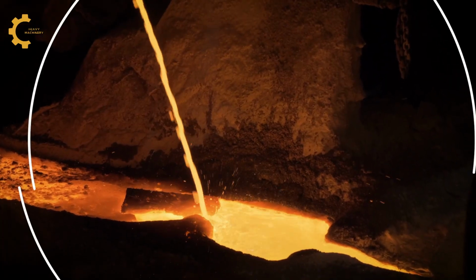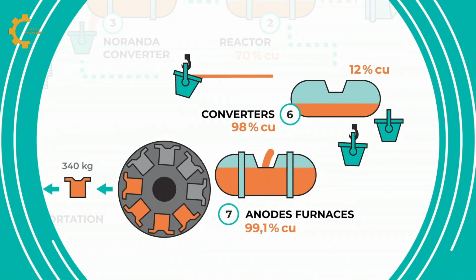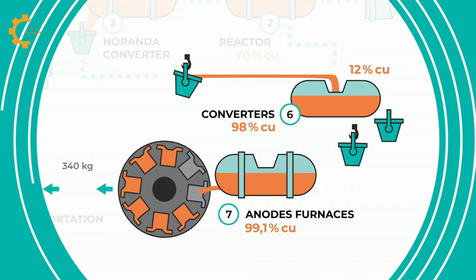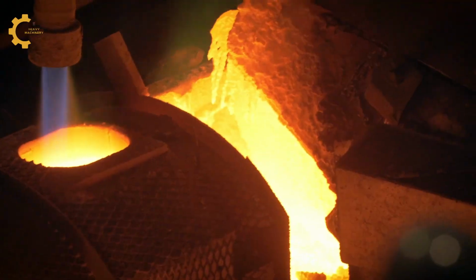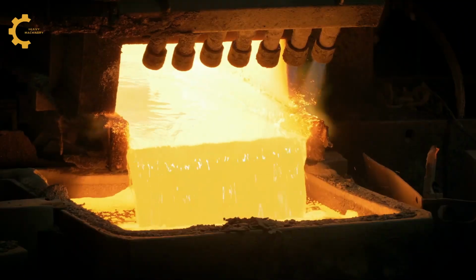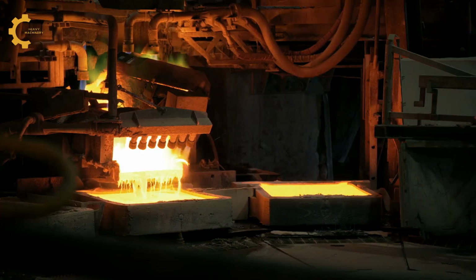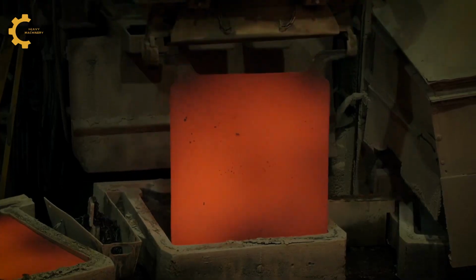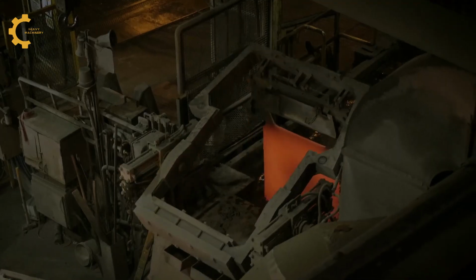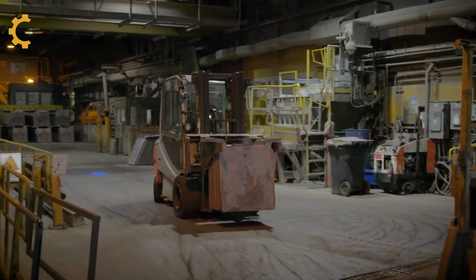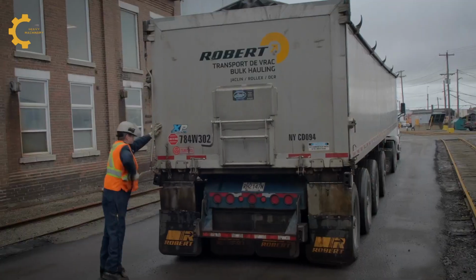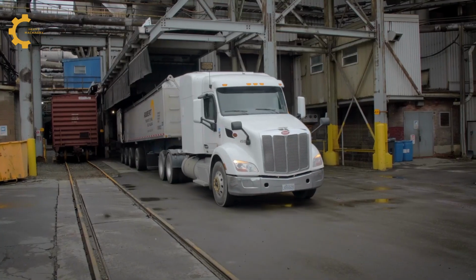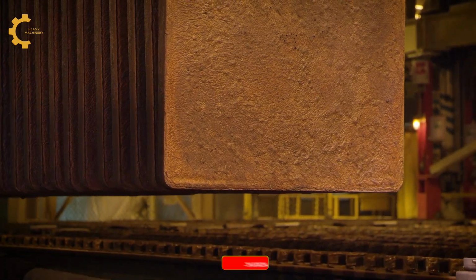Blister copper still contains impurities, so it must be further refined to produce high-purity copper, which is required for most applications, especially in the electronics industry. In fire refining, blister copper is heated in an anode furnace, where air is blown through the molten copper to oxidize and remove any remaining impurities. The refined copper is then cast into large slabs called anodes, which contain about 99% pure copper.